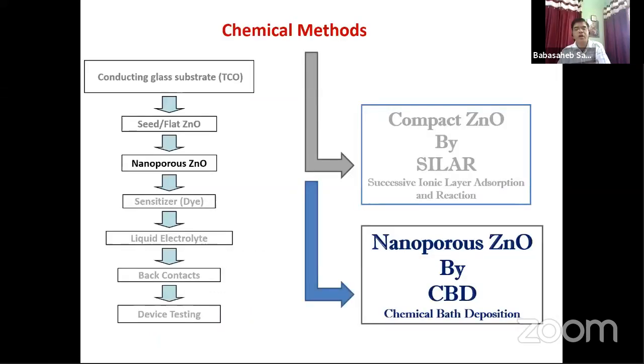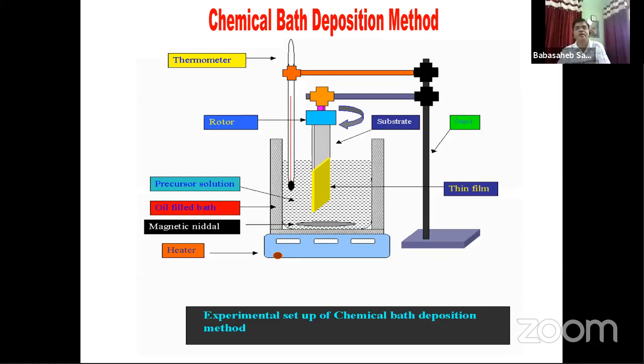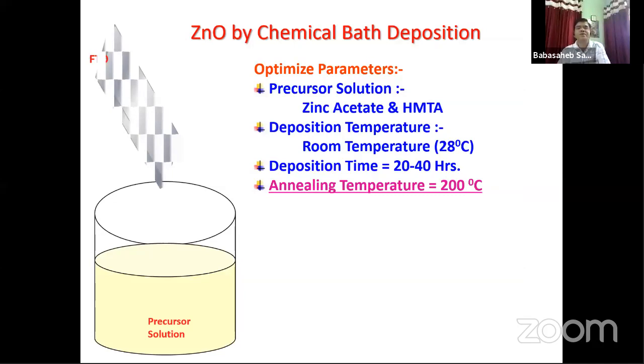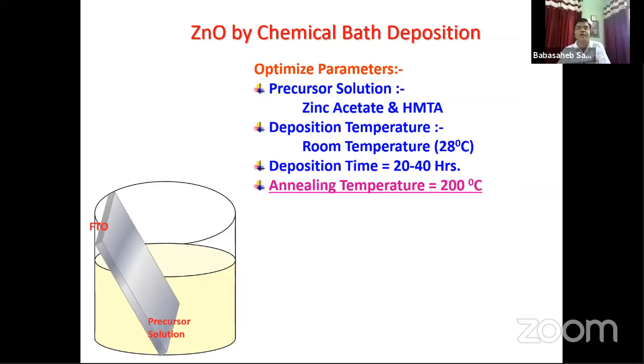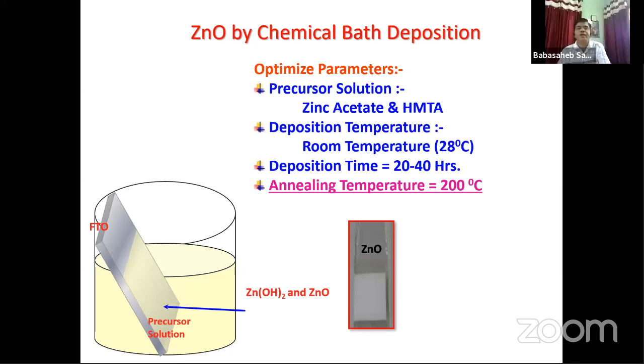So next, nanoporous zinc oxide was deposited by using simple chemical bath deposition, where you can place the cationic and anionic precursor solutions together, and then you can use stirring or no stirring. We simply used zinc acetate with hexamethylenetetramine, and the deposition temperature was just room temperature, that is 28 degrees Celsius. The deposition time was varied from 20 to 40 hours for the optimization. Then after deposition, this film was also annealed at 200 degrees Celsius to remove the hydroxide part from the deposited film.